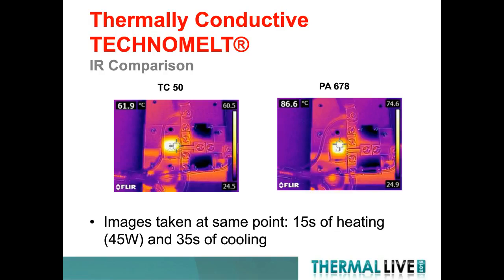The crosshairs show the actual temperature on the upper left: 61.9 degrees C for the thermally conductive material, and 86.6 degrees C for this PA 678, which is a traditional material with 0.2 watts meter K. What you're seeing is that the heat is dissipating more uniformly through the encapsulating layer, and at the exact point where we're measuring, the heat is not reaching the same level as with an insulating material, which is what you would expect to see. It's just a visual representation to reinforce the data from the previous slide.